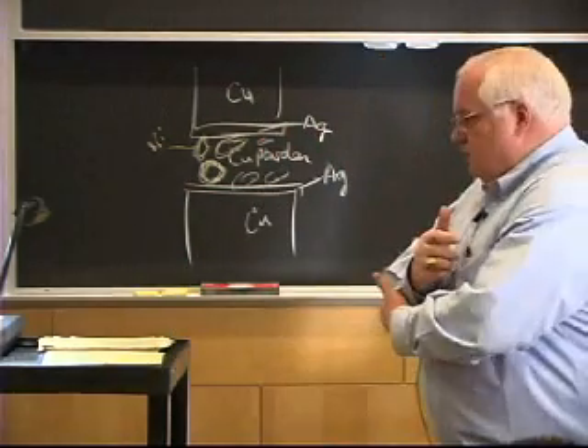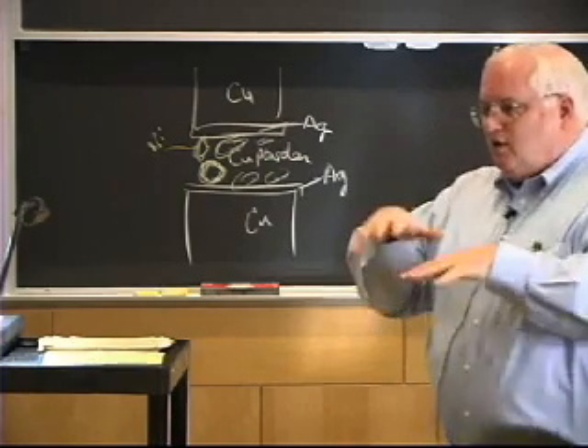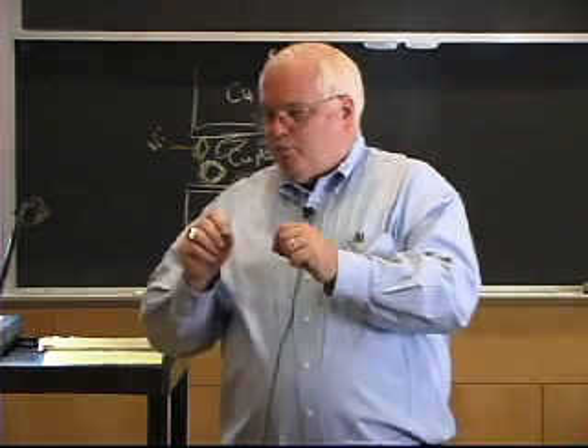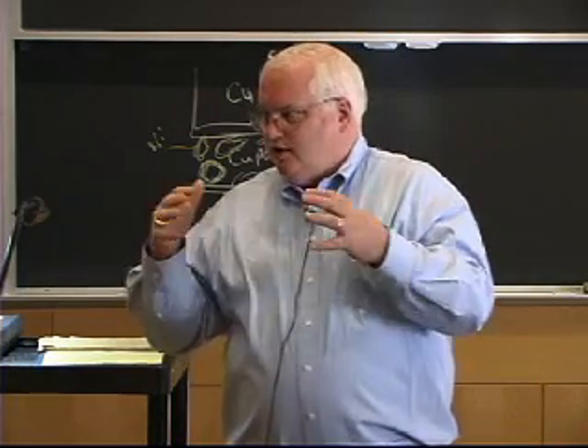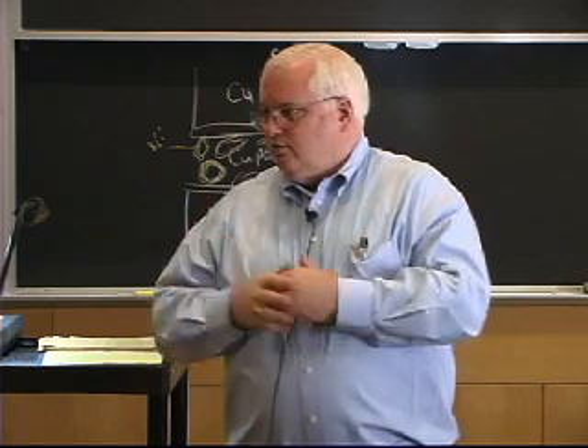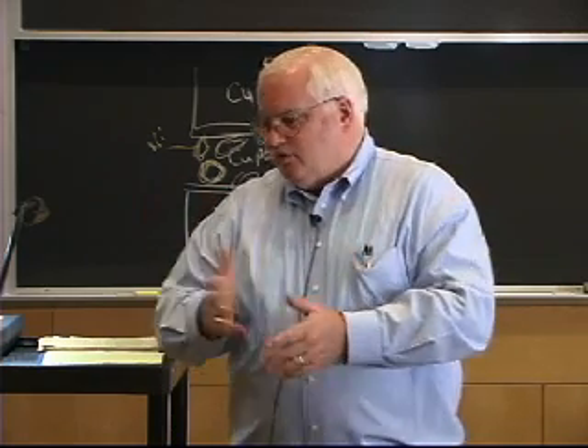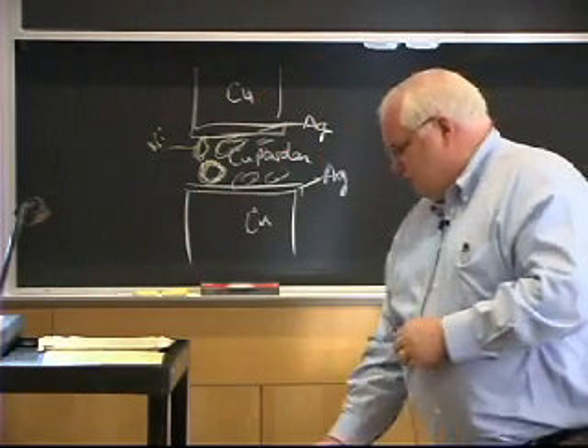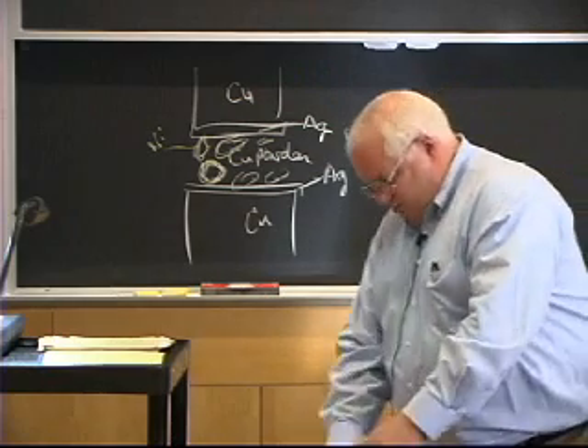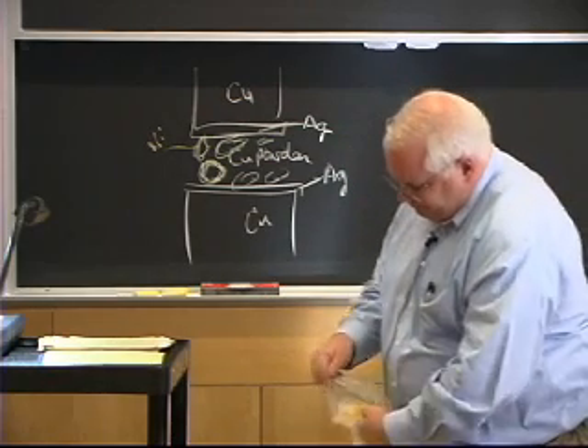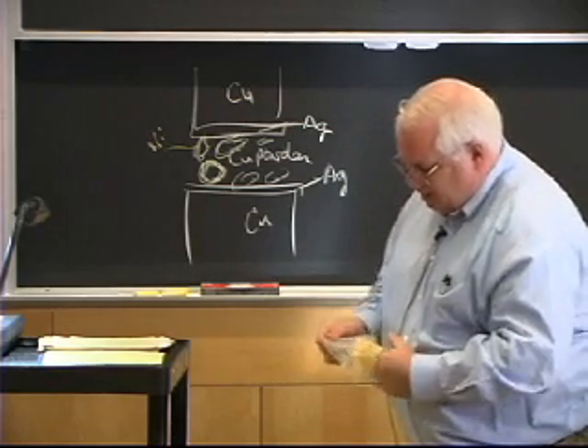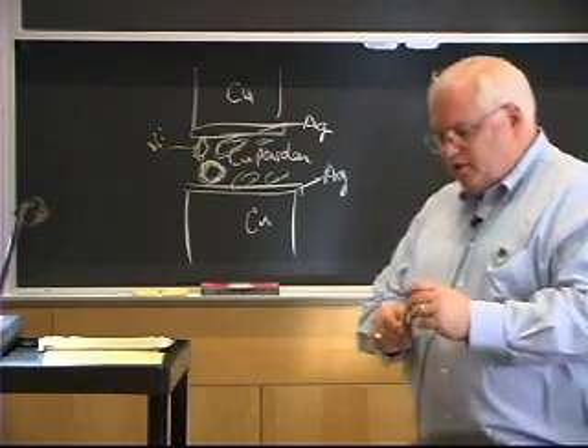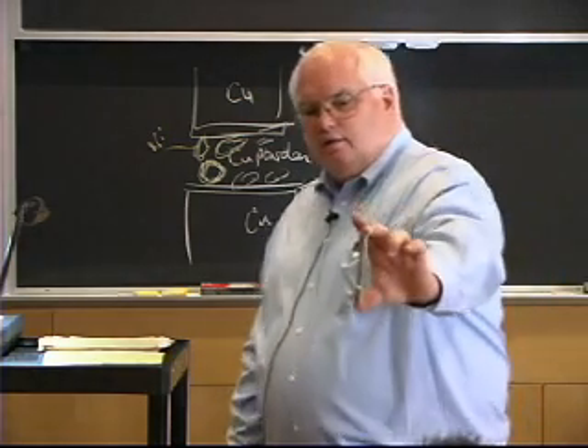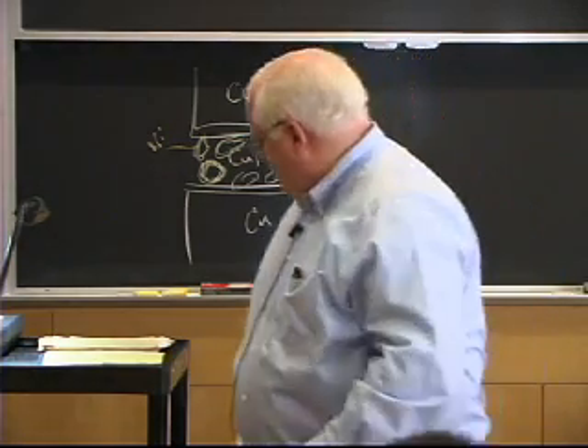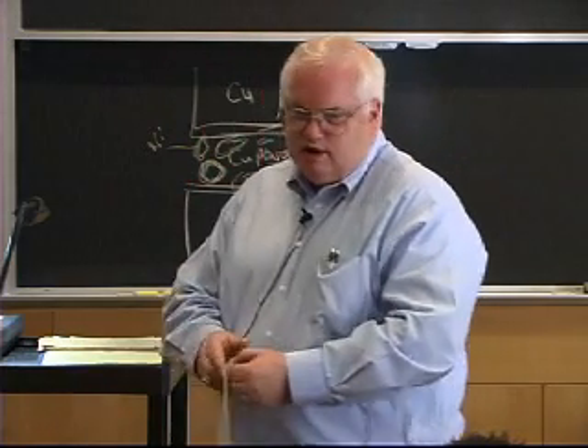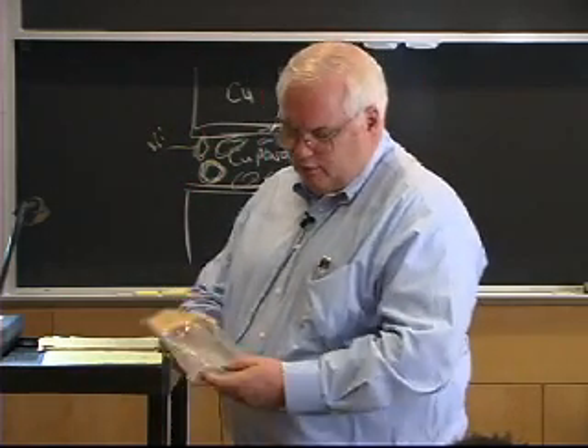People actually do that. I showed the turbine blades, and they start with a paste, and they mix it together. But when you do that, the paste can't be very thick because you have the same problem of everything tends to form up. But if you infiltrate like this, you can get a thicker joint. This happens to be a piece, this is Inconel. So this is a nickel-based alloy that was TLP bonded, also fairly thick. The student was doing tensile tests, and he just gave me some of the tensile specimens he didn't pull.